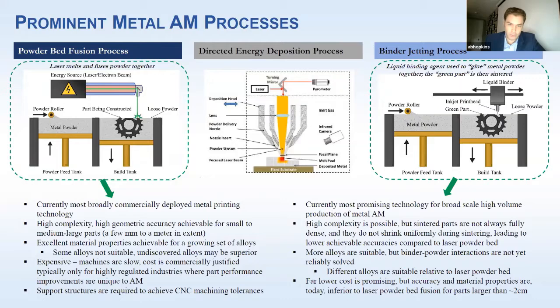If you have a robust parameter set, you get repeatable properties, but that's not a given in the industry right now. In fact, most of the time people struggle with that. And you have these support structures. So when you support, meaning you need to build literally physical supports to obtain high tolerance, or I'll say high geometric fidelity, those support structures need to be broken off or machined off, and again, that costs a little bit of money. So fewer supports are better.